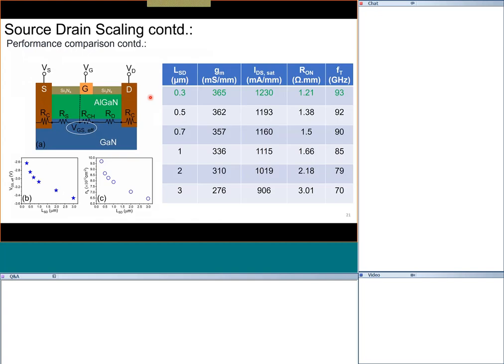All aspects of the transistor improved except breakdown voltage — if you bring the source and drain too close, the operating voltage comes down due to the larger electric field. But the device operates at higher efficiency, so you can expect nearly the same power with better efficiency and lower losses.